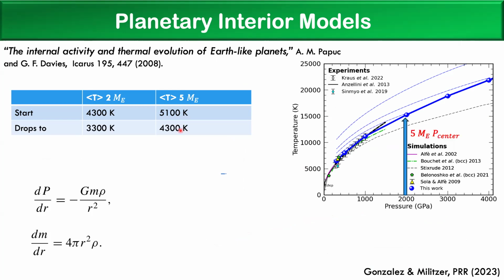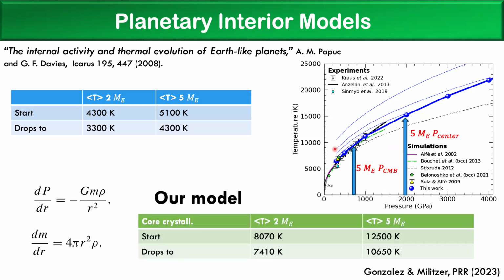But if you look at this diagram that I have obtained for a 5 Earth masses exoplanet, the pressure at the very center is about 2,000 gigapascals. So that means that you need temperatures beyond 15,000 Kelvin to have liquid iron, while the pressure at the core mantle boundary for such a planet will be about 700 gigapascals, which means that you need temperatures beyond, say, 9,000 Kelvin. So according to our models, when the average temperature in the entire core drops below 12,500 Kelvin, then you already start crystallizing an inner core. And when the temperature has dropped below 10,600, then you have completely frozen the entire core, because the pressures and temperatures are not compatible with liquid iron anymore.